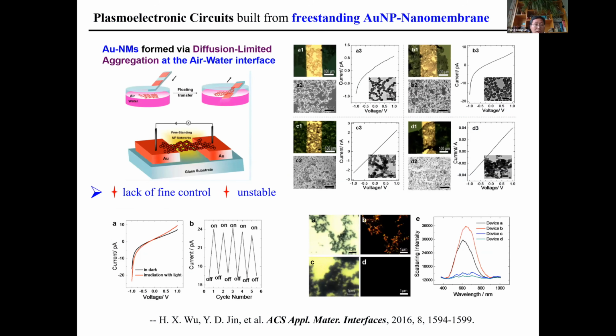So to solve this, we prepared a gold nanomembrane by diffusion-limited aggregation at the air-water interface, and we bridged this membrane over two charge electrodes. We observed some plasmonic origin and response in the IVs of the junction, but the method of nanomembrane preparation still lacks fine control and is unstable.